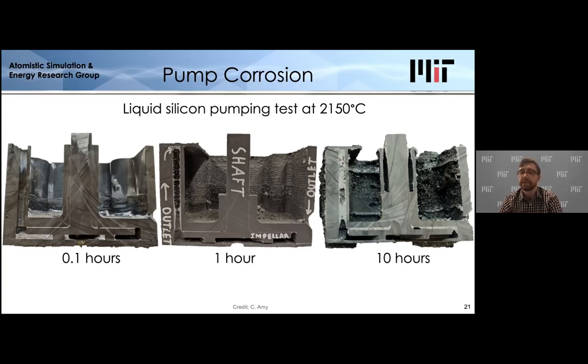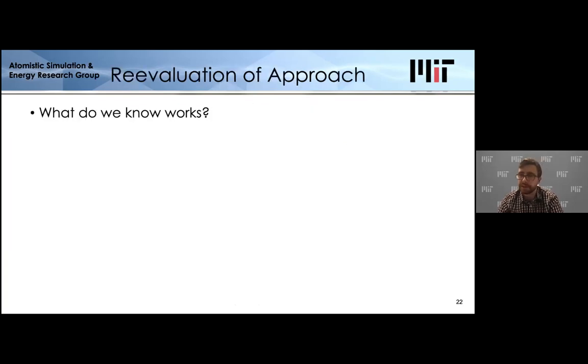So essentially, based on these experiments and a number of experiments done over several months, we determined that silicon is really impractical as a heat transfer fluid or thermal storage medium in this context because it's just too difficult to contain and pump it. It's too reactive, dissolves carbon like crazy, and it's really not the best option for this. So we took a step back to reevaluate our approach and approach it from a view of, well, what do we know works?